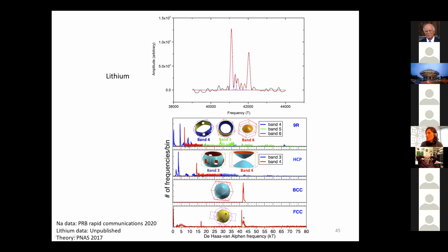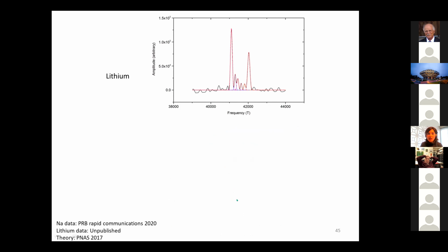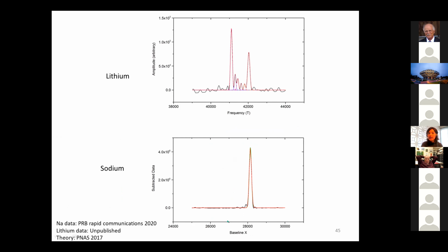And well, you have to calibrate yourself. You have to make sure that you're not doing an experiment and seeing this splitting because of some kind of anisotropy that exists in your calibration of your magnetic field. So we looked at something simpler, something that is even more spherical, and that is sodium. And here is sodium. It's a stunningly sharp peak. It doesn't show any splitting.